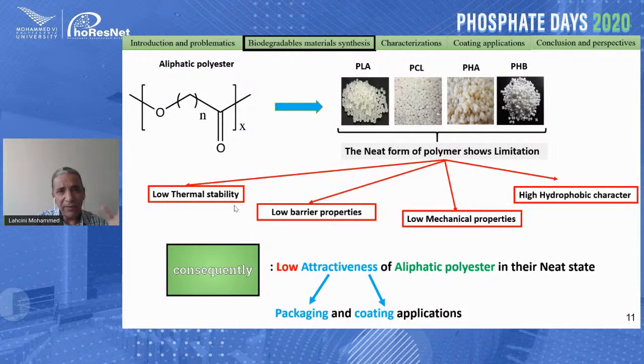So we now have a good catalyst. We prepare high molecular weight polylactide or polycaprolactone, and the aim of the application was packaging or coating fertilizers. But these aliphatic polyesters present some limitations. They have low thermal stability, low barrier properties, and low mechanical properties. They are also highly hydrophobic, and for coating fertilizers the hydrophobic character sometimes presents a drawback. Then we should improve these properties to use them for packaging and also for coating fertilizers.